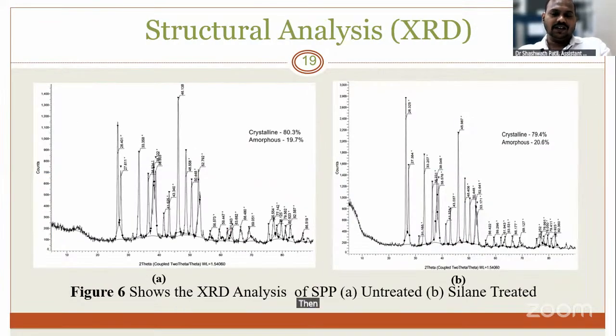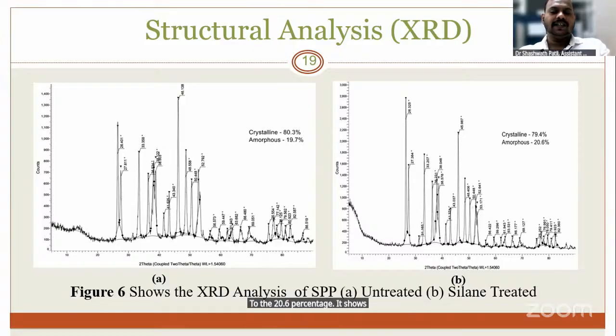Then we did the structural analysis. In the structural analysis, as you can see, it shows the crystallinity percentage and amorphous percentage of the untreated and treated samples. The major peaks were around 20 to 50 degrees, as it was calcium carbonate in the form of calcite. But after treatment, the crystalline form was reduced slightly and the amorphous content increased from 19.7% to 20.6%. It shows that without disrupting the original crystalline structure, the silane has been bonded to the squid pen powder.